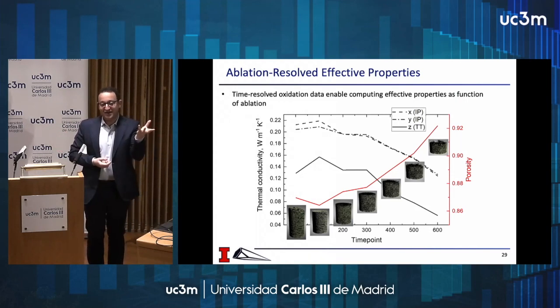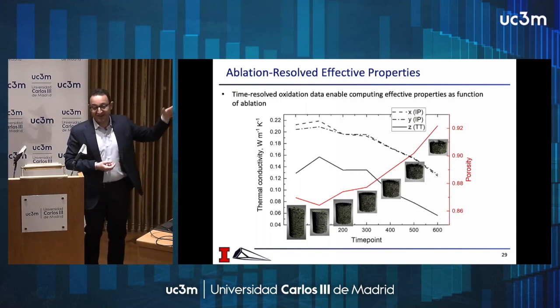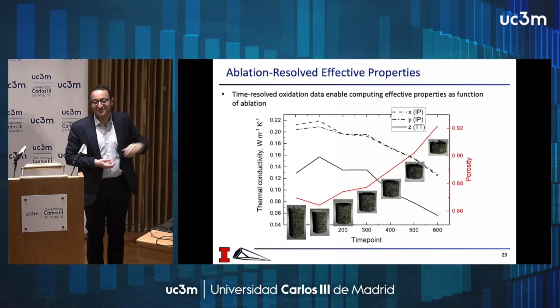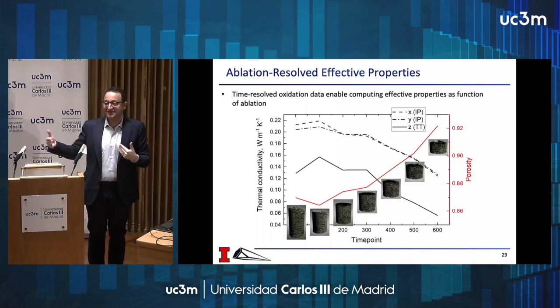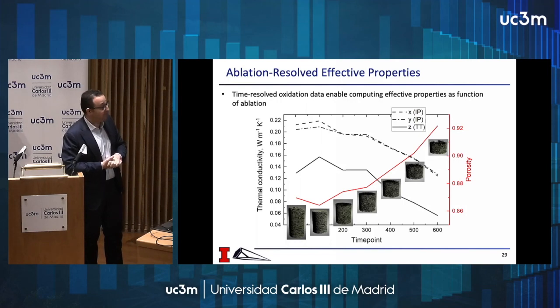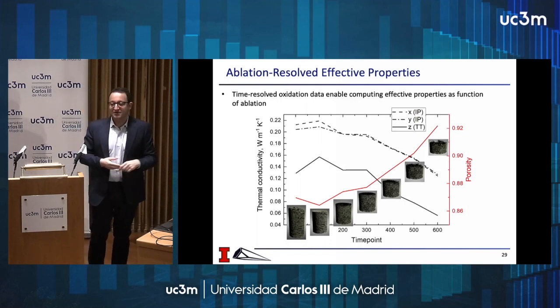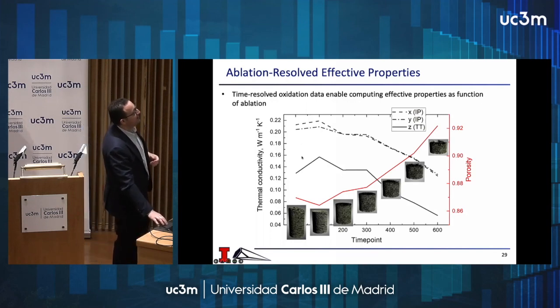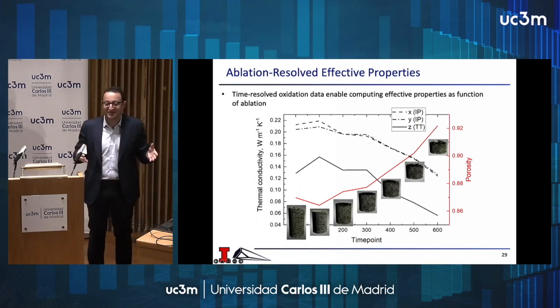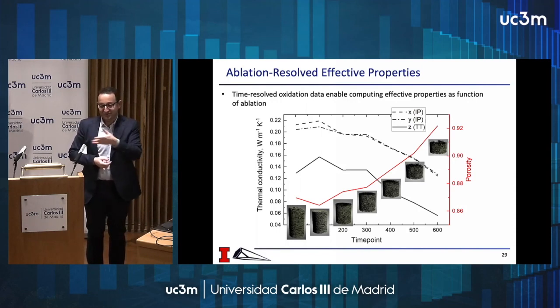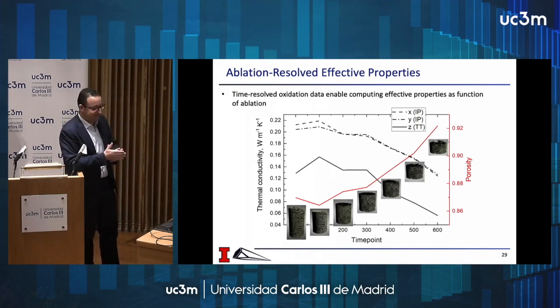So now that you have a resolution of the dynamics of the material in time, you can compute all the effective properties. I'm showing the thermal conductivity here as an example, as it evolves in time, and as the material decomposes. This is a sort of breakthrough in this field, in the sense that what we were doing before is we had a measurement for the virgin material, a measurement for the fully decomposed material, and we were doing a linear interpolation between the two. But now that we have temporal resolution of the dynamics of how this evolves, we can compute effective properties as a function of time and as a function of decomposition.